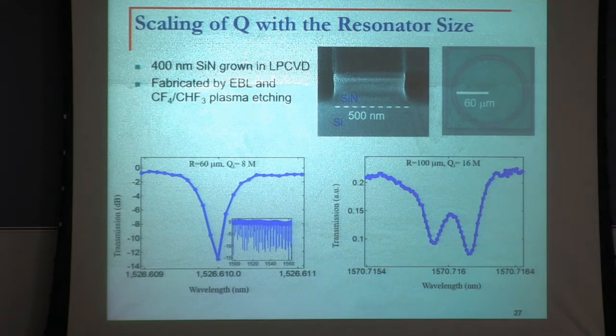These are some examples of the fabricated devices, silicon nitride on a silicon wafer. You can see that we have got Qs of 16 millions. And now by adding chemical mechanical polishing, or CMP, to our system through the new addition to IEN, we're expecting to easily get above 30 million, which is state of the art. So that's like an order of magnitude better than silicon.